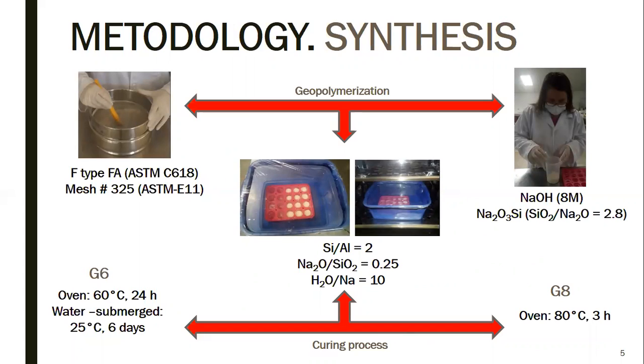The fly ash used in this study is an F-type fly ash that was passed through mesh number 325. For the alkali activator solution, a mix of sodium hydroxide pellets at 8 molar and sodium silicate solution with modulus of 2.8 was used. They were mixed together for geopolymerization in the following conditions: silicon aluminum ratio of 2, sodium oxide silicon oxide ratio of 0.25, and water sodium ratio of 10.